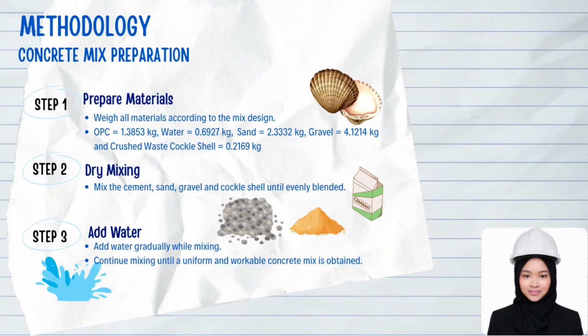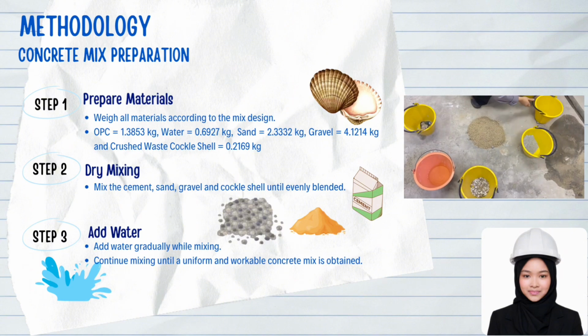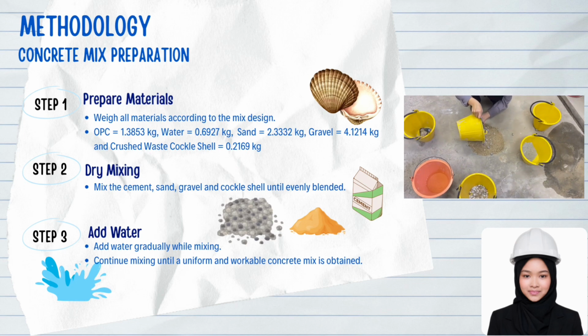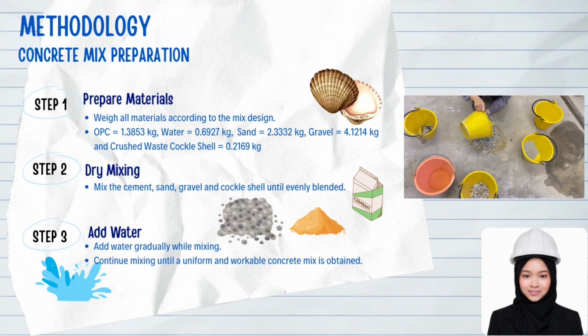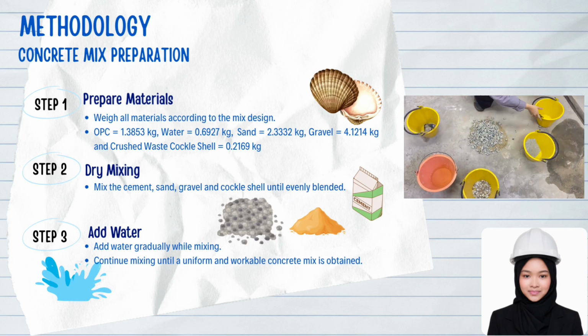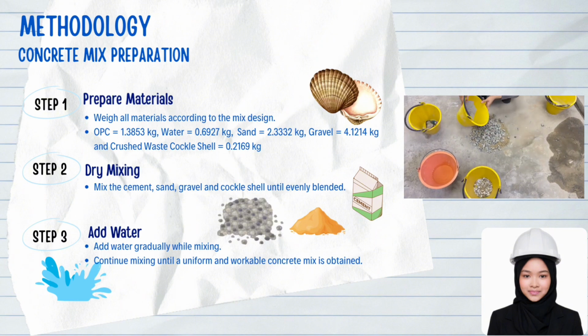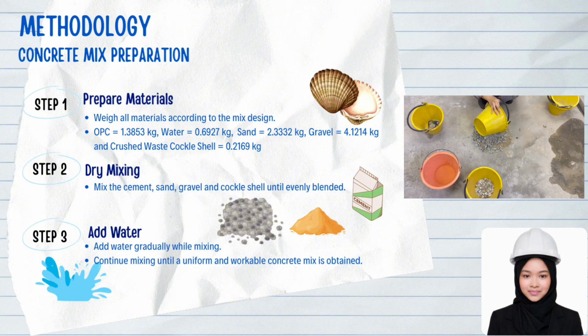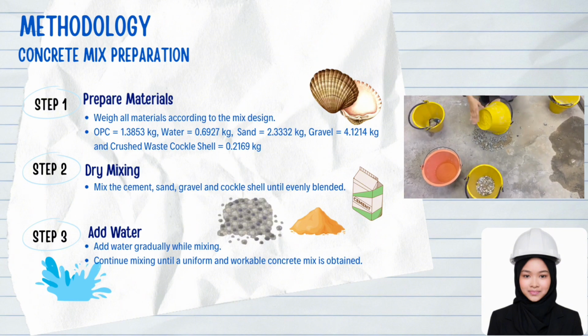The second stage is the concrete mix preparation. All materials were first weighed according to the mix design. The mix consists of 1.3853 kg of cement, 2.3332 kg of sand, 4.1214 kg of coarse aggregate, 0.6927 kg of water, and 0.2169 kg of crushed cockle shell.